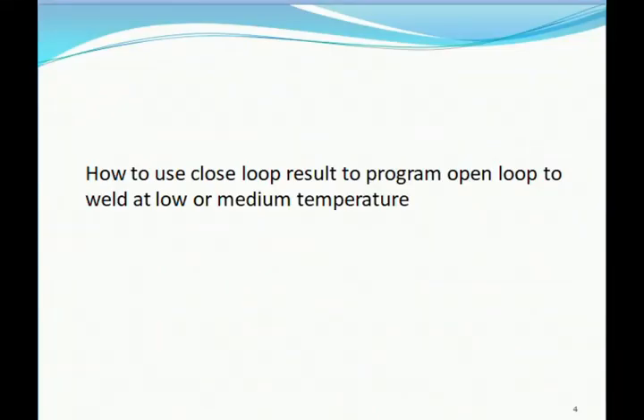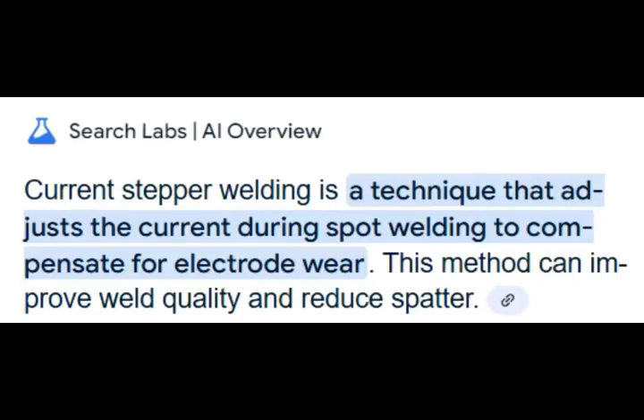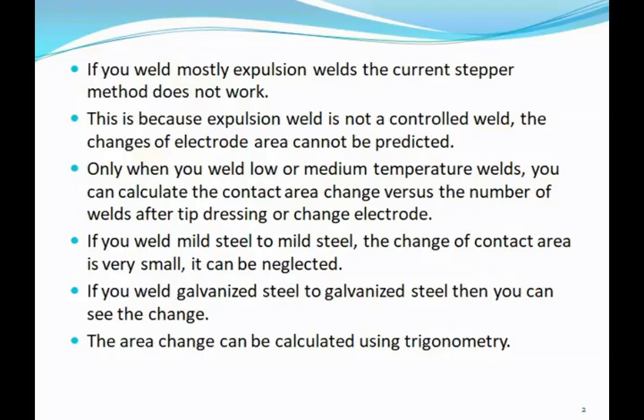How to use closed loop results to program open loop to weld at low or medium temperature. Current stepper welding is a technique that adjusts the current during spot welding to compensate for electrode wear. This method can improve weld quality and reduce spatter. If you weld mostly expulsion welds, the current stepper method does not work. This is because an expulsion weld is not a controlled weld, and the changes of electrode area cannot be predicted. Only when you weld low or medium temperature welds can you calculate the contact area change versus the number of welds after tip dressing or changing the electrode.